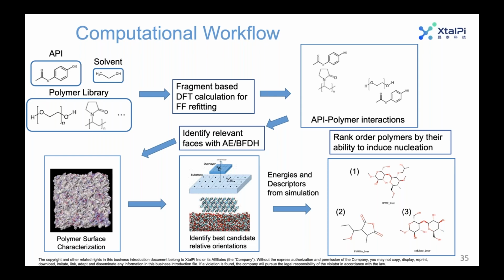Yeah, so let's take a high aspect ratio crystal, for example. Let's imagine that one of the unit cell parameters is just really long compared to the other two. The way that the unit cell is for that crystal, you'd be almost predisposed to needles. So it's very unlikely that just changing the temperature or the solvent composition is going to have a profound enough effect on the growth rate that it would change that molecule from something other than a needle. And that's really where polymers or additives might come into play, right?